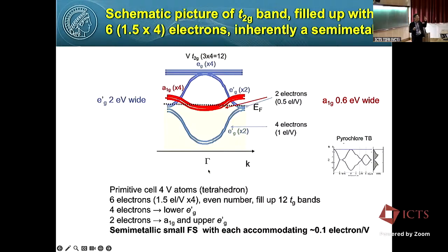And in a pyrochlore lattice, okay, the primitive cell contains one tetrahedron. So that means you have 4 vanadium in the primitive cell. Right? So I said we have 1.5 d electrons per vanadium, but we have 4. That means we have 6, an even number of electrons in the primitive cell, and that's quite important. Actually, we long dismissed that point. Okay, so 6 electrons fill up 12 T2G bands. 3 times 4 equals 12.